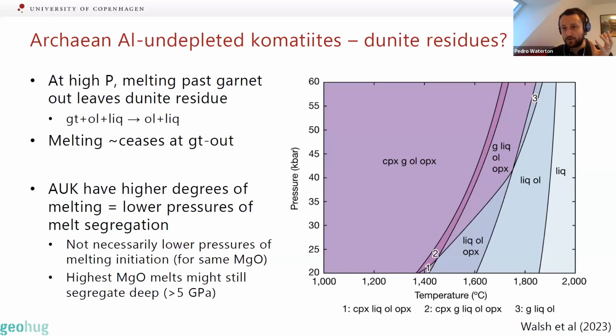for the high MgO ones, the pressure of melting initiation is actually probably quite similar to an aluminium depleted komatiite. The only difference is that the extent of melting is higher, such that you completely exhaust garnet in the source. And again, the pressure of melt segregation can be really deep, because you might be hitting this garnet out curve at past 180 kilometers or 6 gigapascals.